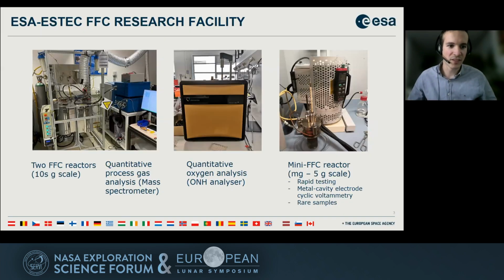At ESA in the Netherlands, at the center called ESTEC, we have different equipment for advancing the research. We have two FFC reactors where we can process samples between 10 to 30 grams of lunar regolith. We have a mass spectrometer to analyze the gas we extract. But it's always good to cross-check the oxygen you have left in your material. For that, we have a quantitative oxygen analyzer where we add a tiny piece of partially reduced or fully reduced sample after it was processed by the FFC, and we can see how much oxygen was left inside. And for other quick testing, we have a smaller scale setup.